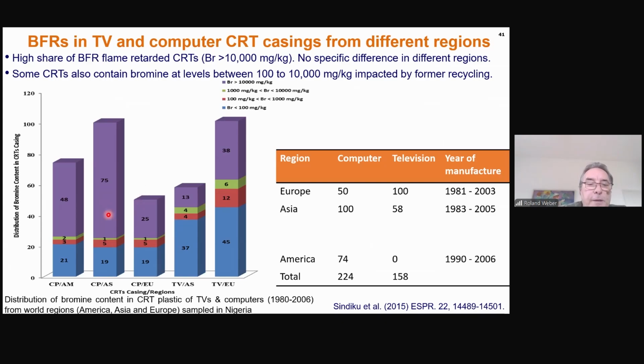Also, when you see this one in purple, these were fully brominated flame retardant samples, and this one in green and in red, they contained brominated flame retardant at a level of 100 to 10,000 milligram per kilogram. And this concentration is considered to stem only from recycling and not from full application of flame retardant, because normally you need more than 3% of brominated flame retardant in your television.